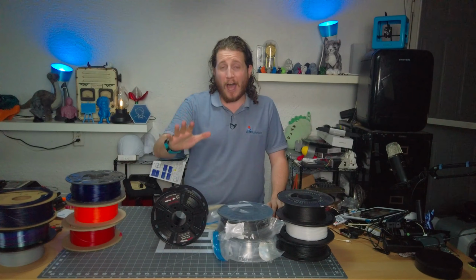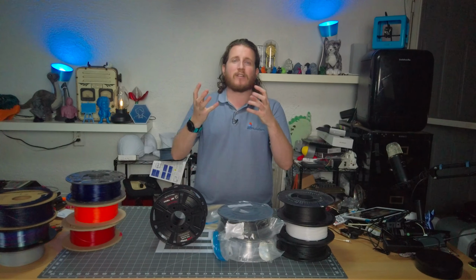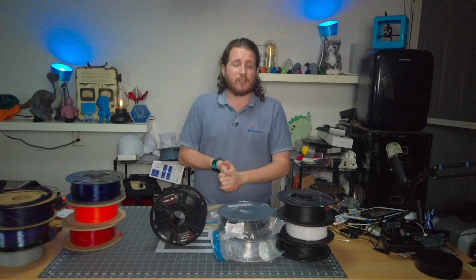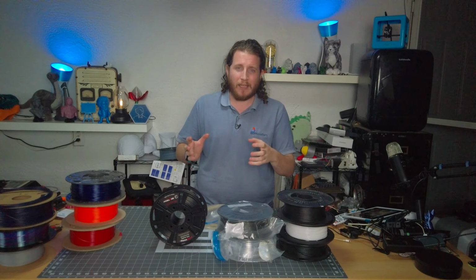We only add a little bit of cooling when we do bridging to allow that material to actually shrink as we need it to get really fancy bridging. But you'll notice on some prints, the layers might start to separate. That is because as ABS cools, it tends to shrink. It is common that if you're going to be printing ABS, that you add 0.5% and scale your parts up ever so slightly because that material is going to shrink.